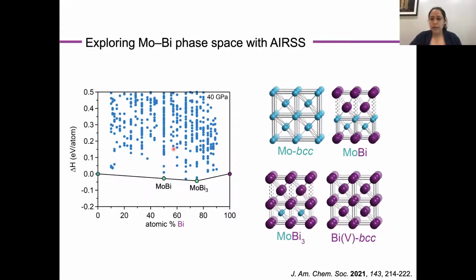And I think this speaks to the fact that there is very little energetic preference for placing an atom of a given type on a site in this BCC or distorted BCC type lattice. And so while we limited ourselves in this case to small unit cells as a place to start, I think what we're capturing is actually a tendency towards longer range order or even alloying in the system that would be otherwise rather difficult to get at with these high throughput calculations.